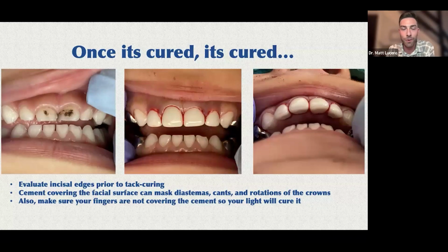But yeah, you just got to make sure before you tack cure, make sure everything is exactly where you want it. So I really emphasize to people, take your time at that stage. You have a full minute and a half of working time. Don't rush it. If you need to move crowns, move them. But once you tack cure, you're done. And you can see there the alignment was off, and even on that incisal view, you can see it's rotated a little bit too.